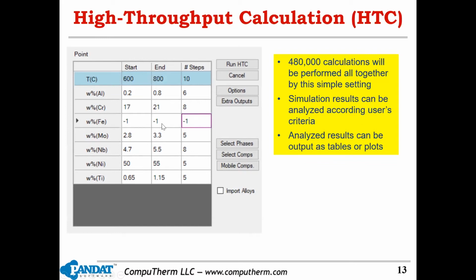Here, iron is the balance element. So in other words, while I give the other elements, the composition is fixed, then iron will take the rest of the amount, so it makes 100%, all right? And I can change the temperature. For example, I change it from 600 to 800 degrees centigrade, and then I give 10 steps. So with this setting, a total of 480,000 calculations will be performed all together with this simple setting.